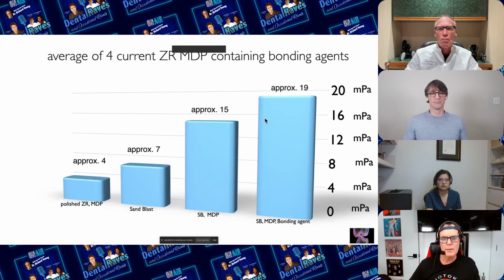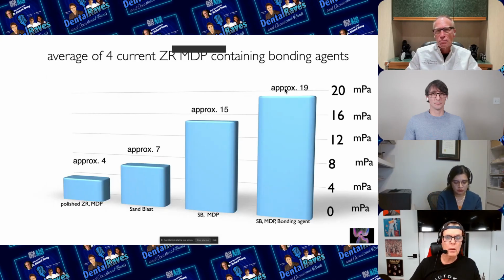All right, then I thought about this, and this is the way I've been doing it for years. If I'm going to bond zirconia, I would do the sandblasting, clean the surface, of course, then put the MDP primer on. But the MDP primer, I was a little bit concerned, didn't completely wet the surface. The MDP primer bonds to an oxide on one side and bonds to a resin on the other side. So I just put a low viscosity resin, just a regular bonding agent that you'd put on the surface of your glass or surface of a tooth or something like that. Then the cement on the top. That got the best bond strength. So we were up close to 20, 19, 18 megapascals.